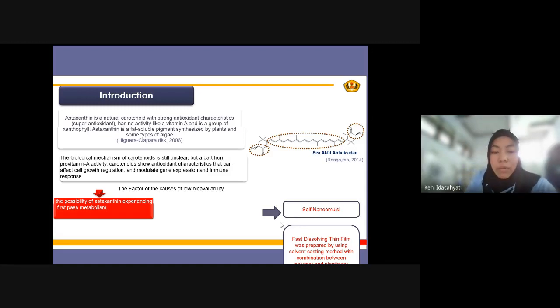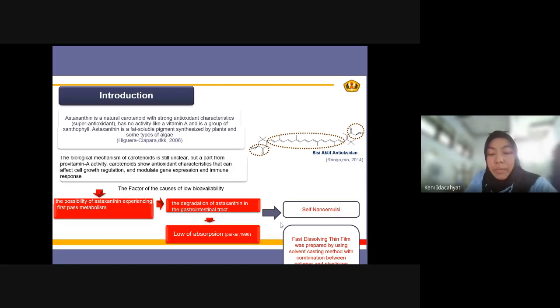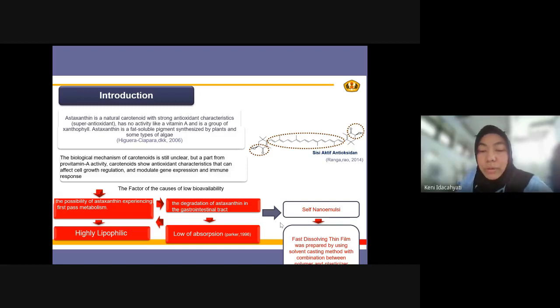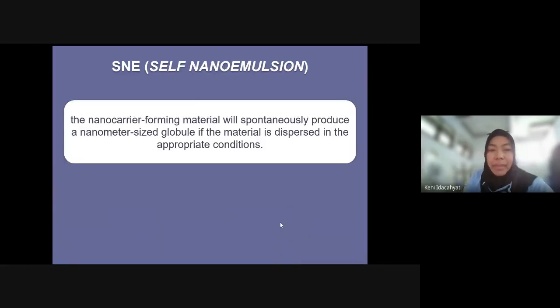There are many causes of low bioavailability of astaxanthin. The first is the possibility of astaxanthin experiencing first pass metabolism, degradation of astaxanthin in the gastrointestinal tract, low absorption, and high lipophilicity. Because of these factors, we developed a SNEDDS nanoemulsion method, and incorporating it into a fast dissolving thin film was preferred, using the solvent casting method with a combination of polymer and plasticizer. And then what is the SNEDDS nanoemulsion? The SNEDDS nanoemulsion is a nanocarrier-forming material which spontaneously produces nanometer-sized globules when the material is dispersed in aqueous conditions.